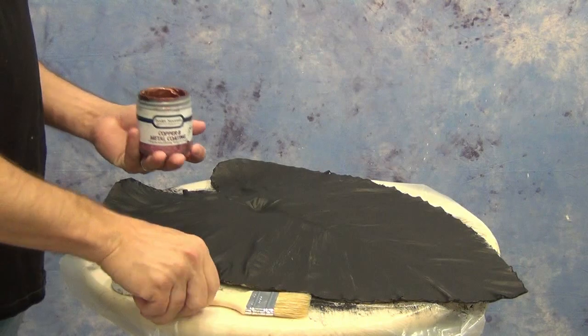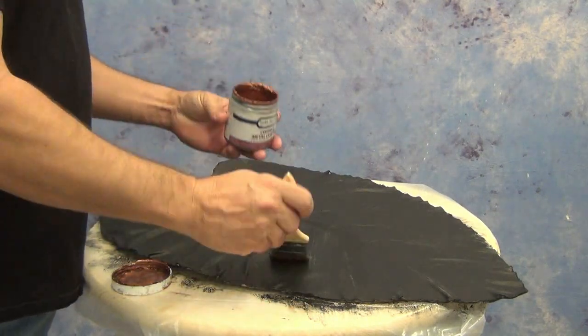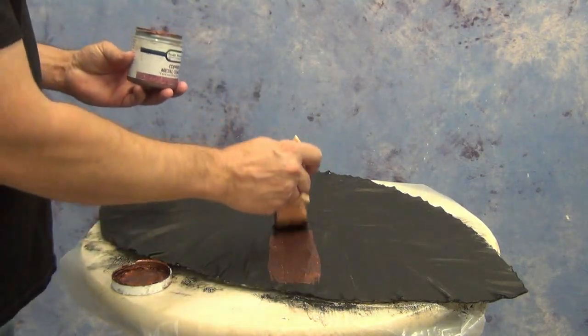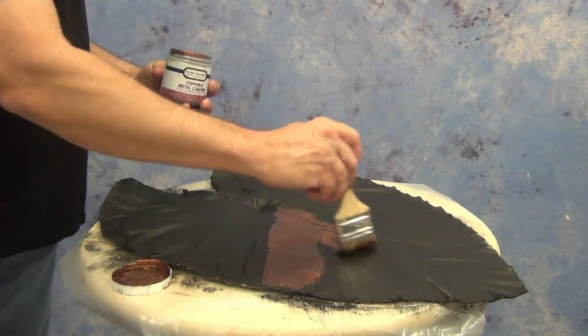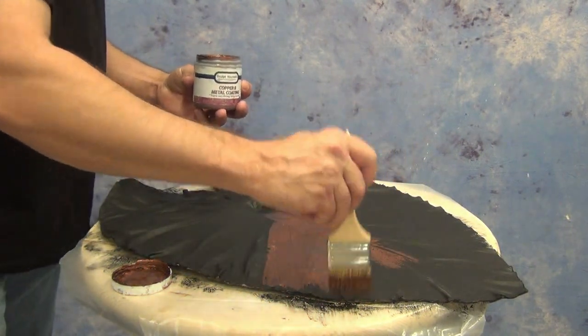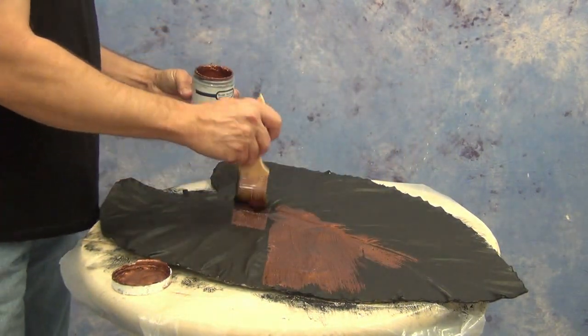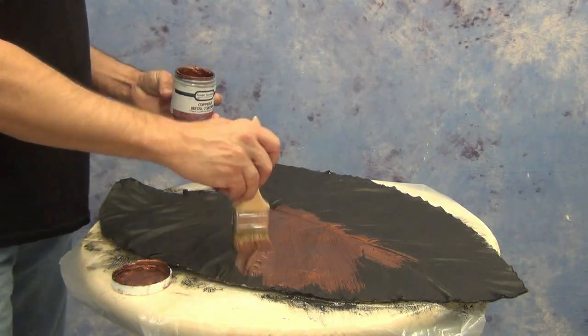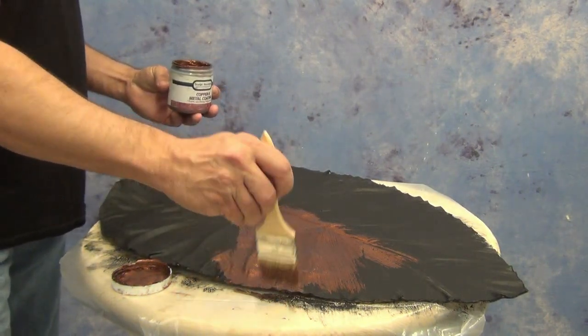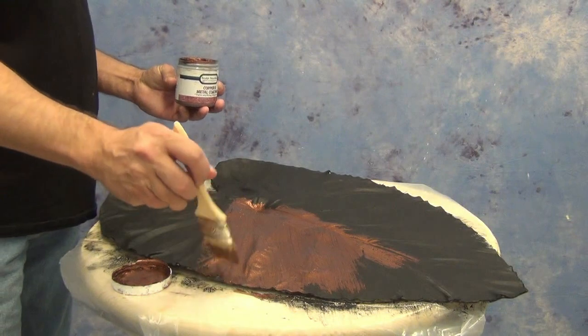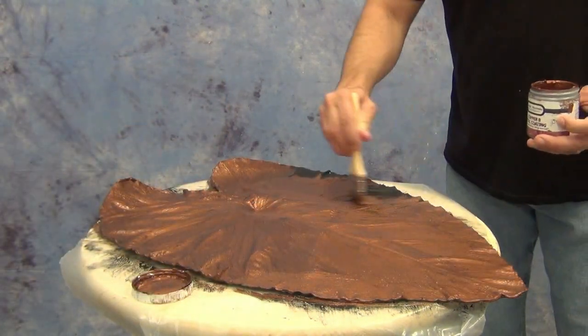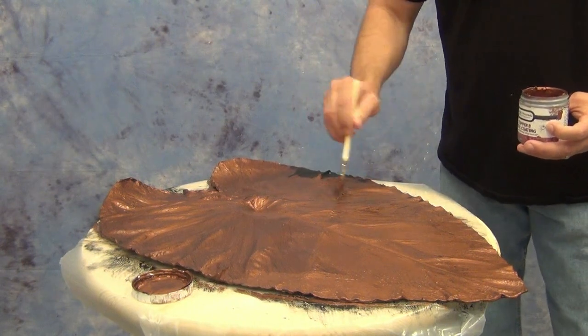But the copper B metal coating, unlike a copper paint, actually contains real copper powder and a lot of it. So what it does is it allows us to have a surface that will actually oxidize like real copper because it is. So what we're going to do is put on a base coat of copper B and brush that all over the surface of our part. And then we're going to come back and stipple out those brush strokes. And that's an important step.